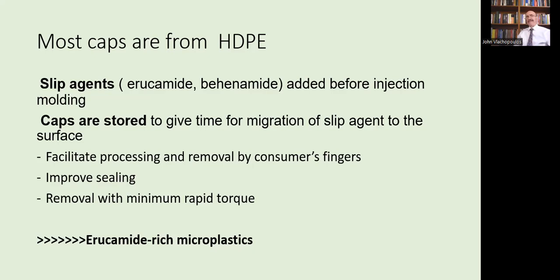erucamide and behenamide. Now, the caps also must be stored because the erucamide or behenamide are added to the product, to HDPE, before injection molding. So it needs some time for the slip agents to migrate to the surface, because on the surface is where they are needed. They're not needed inside, right? So we want this material to migrate to the surface, and because of their crystal structure, they have some plates, and these plates result in the slip, which is very easy, and then we can have a clean removal of the cap from the bottle.